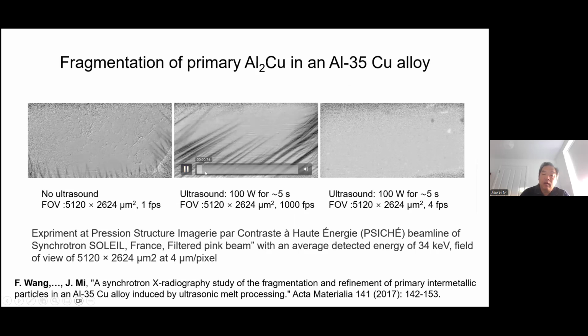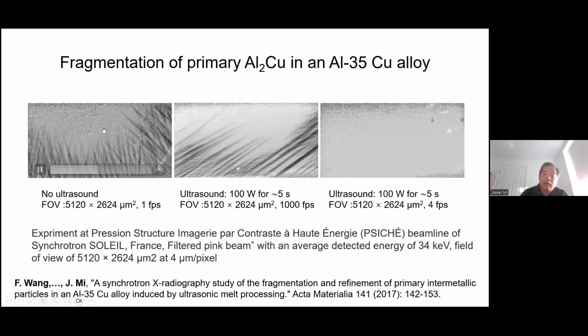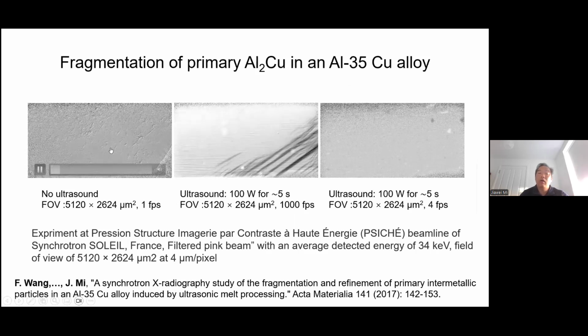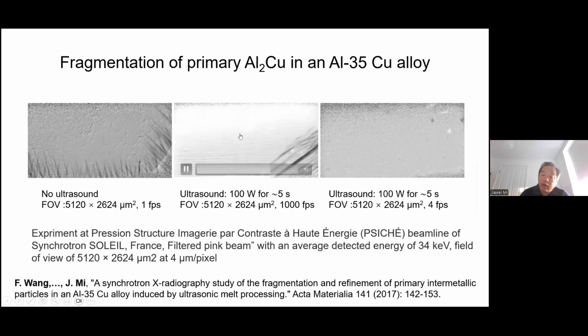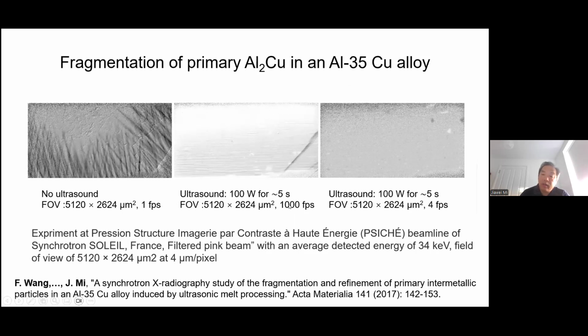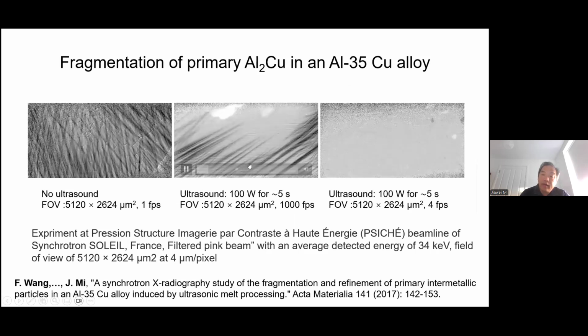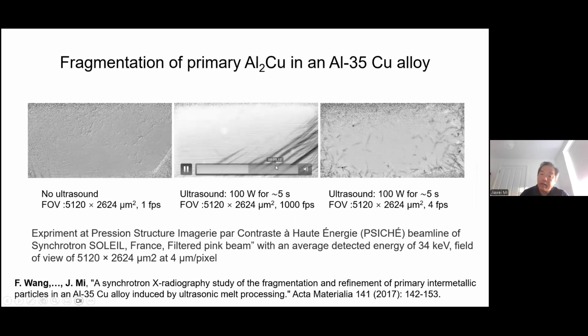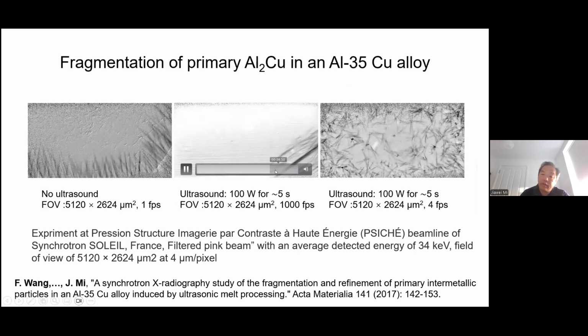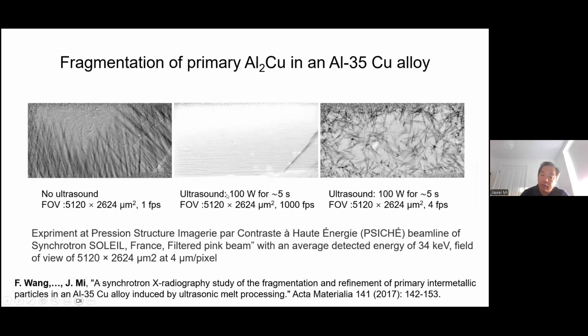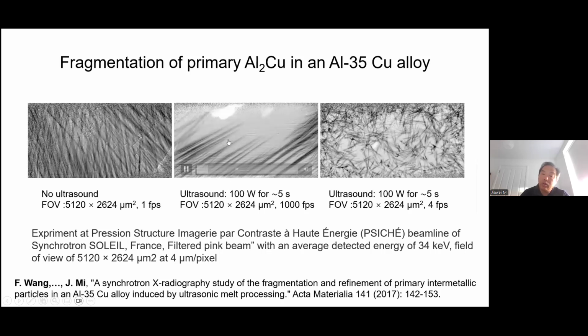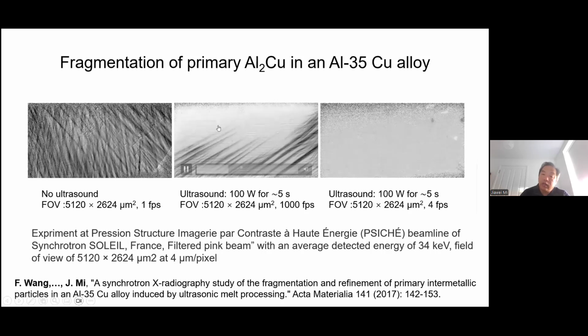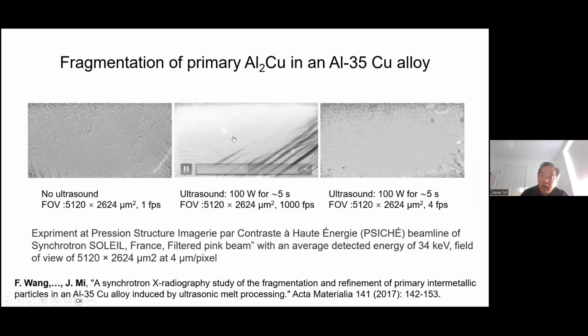If we look at this particular phase growing without any ultrasound, it is growing into a very long strip. If you have ultrasound, it can quite effectively break off the growing phases. Very, very effective. You can see that happening in a few seconds. But here you still see the strong swirling flow.